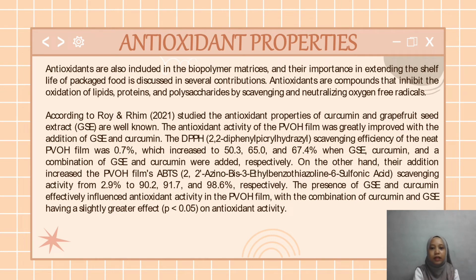The DPPH scavenging efficiency of the neat PVOH film was 0.7%, which increased to 50.3, 65, and 67.4% when GSE, curcumin, and a combination of GSE and curcumin were added respectively. On the other hand, their addition increased the PVOH film's ABTS scavenging activity from 2.9% to 90.2, 91.7, and 98.6% respectively. The presence of GSE and curcumin effectively influenced antioxidant activity in the PVOH film, with the combination of curcumin and GSE having a slightly greater effect on antioxidant activity.